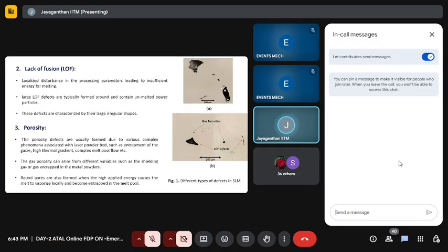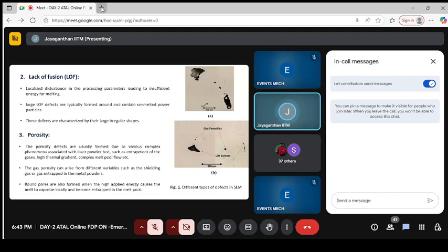And again, there could be, for example, porosity also. Porosity could form due to complex phenomena associated with the laser and powder itself. If you don't use an appropriate laser energy source, we end up seeing this kind of problem. So for example, metal may evaporate also. That in turn will cause entrapment of gases actually. That's where laser energy density needs to be known for each material.